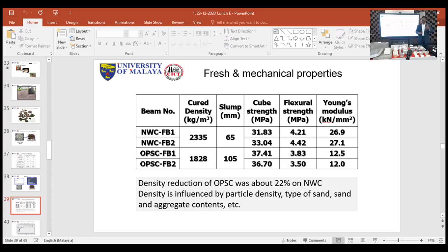There you can see the difference of almost 20% reduction in the density. It's lightweight concrete, less than 2000 kg per meter cube. Then the workability is quite acceptable, and the compressive strength, cube compressive strength, was almost identical. It's in the range of 30, and we can see the flexural as well as the modulus of elasticity.